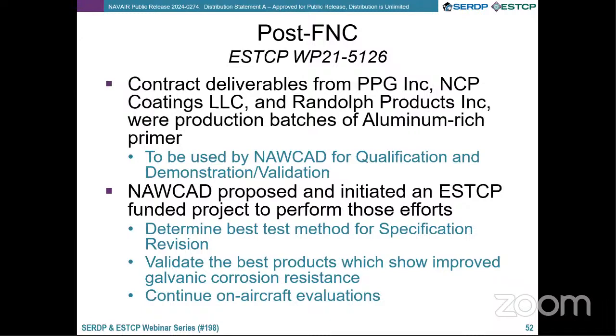To be fair, we had started evaluating the early immature formulations as well, and they had some issues that were meant to be worked through as we continue to mature. But we were able to use those to show that even in an imperfect coating, the aluminum rich pigment did show promise for being a corrosion inhibitor in the field.